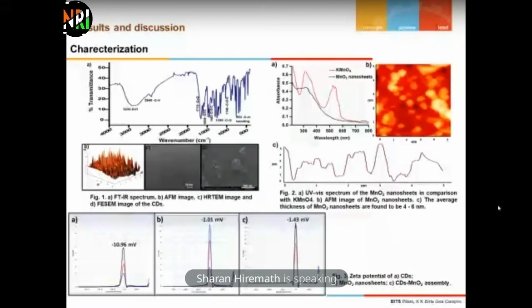Next, for the MnO2, we have carried out the UV study, where the peaks of KMnO4 are now being reduced to the peaks of MnO2. It shows that the KMnO4 has been transformed to MnO2, and also AFM shows the sheet layer, as each sheet has a thickness of 5 nanometers.